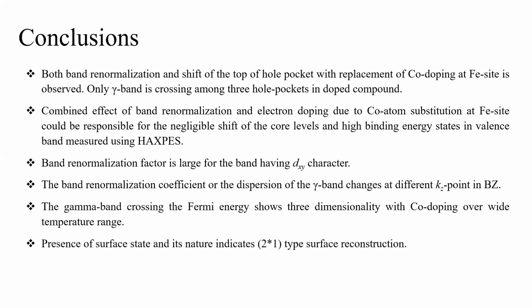Do you expect any other kind of doping can increase the superconducting temperature for this compound? People have doped at all three sites: the calcium site, iron site, and arsenic site. At the iron site, I think people have doped three to four elements. I remember cobalt, nickel, iridium, and early on I think platinum also. Among these, three show a superconducting phase, but other element doping doesn't show any superconducting phase. Of course, it suppresses the magnetic ordering, but doesn't show any superconductivity.